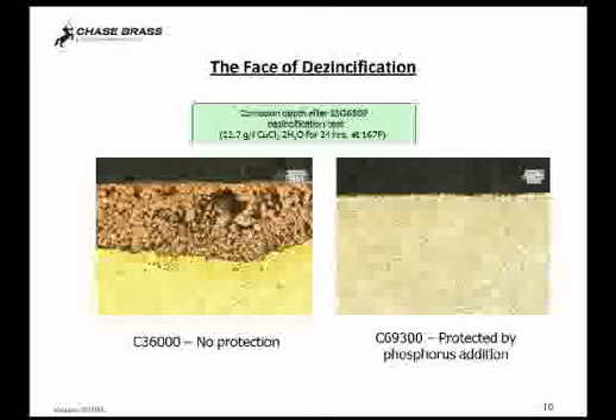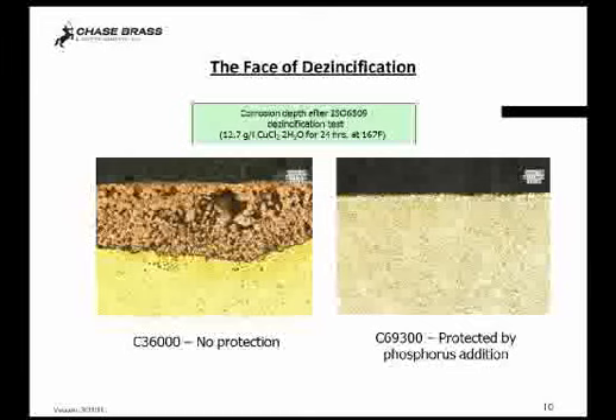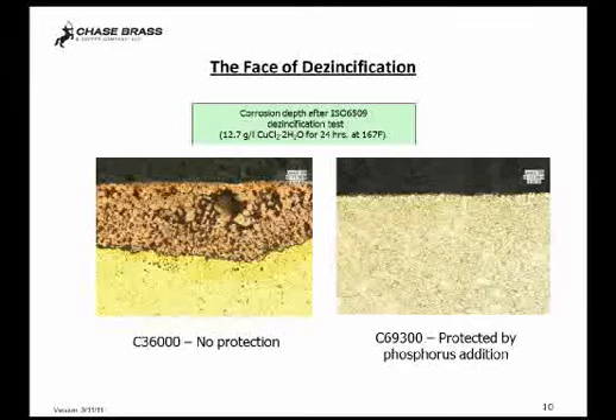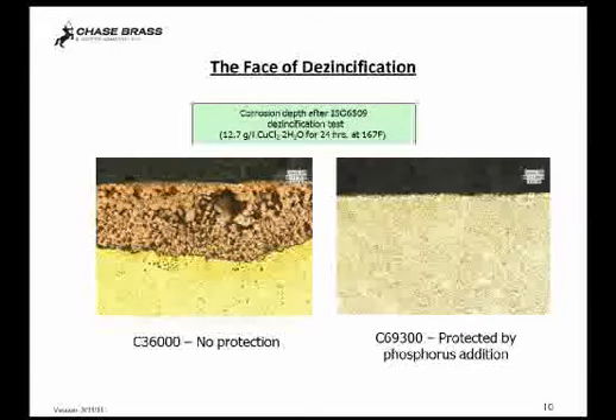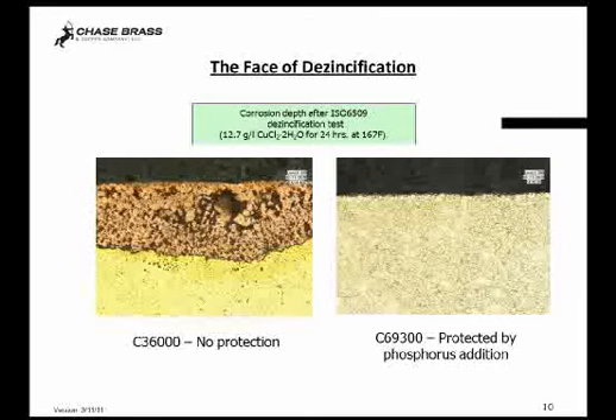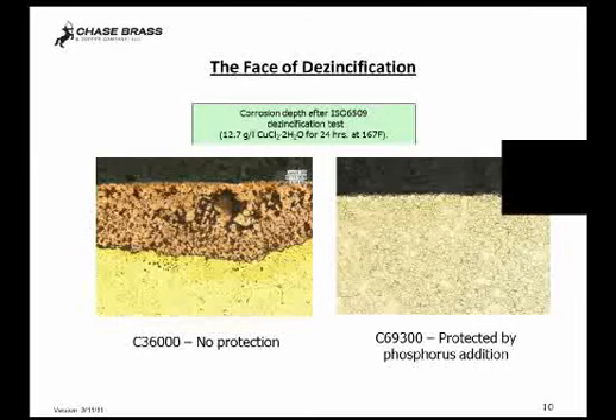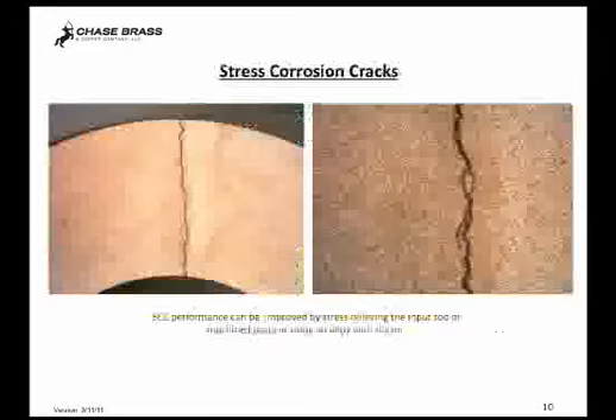Brasses can be protected from this kind of dezincification corrosion either by reducing the zinc content to below 15%, but that makes it a lot harder to produce, or by adding an element that protects the brass, like the phosphorus content in alloy 693, or arsenic, for example, in alloy 35330. Those types of elemental protections or alloying addition protections work only as long as the zinc content in the alloy is below 36% and the proper alloy and manufacturing controls are in place.